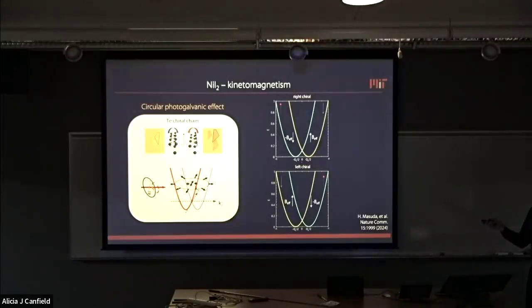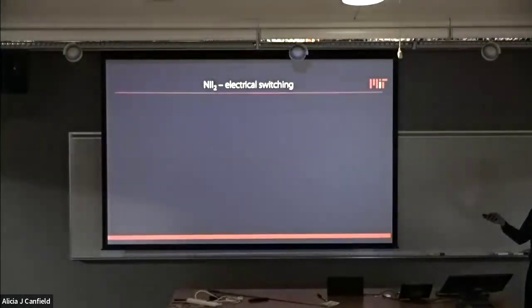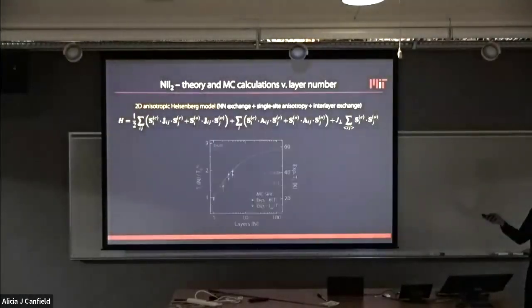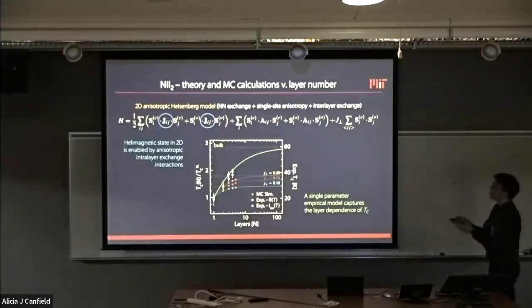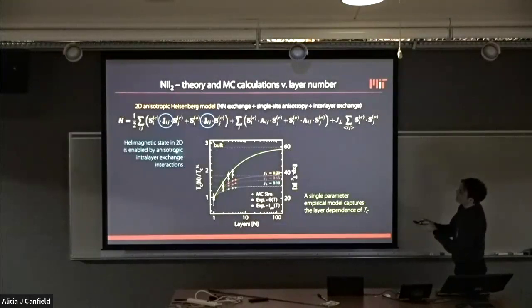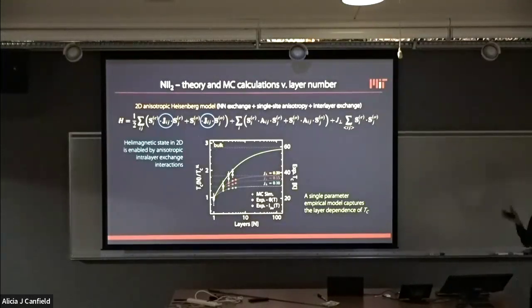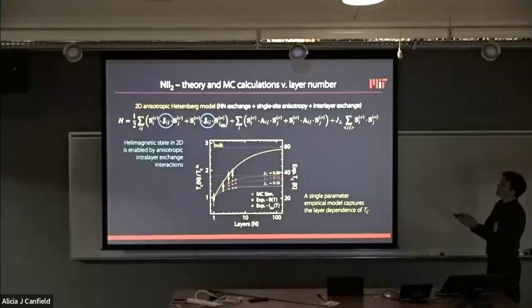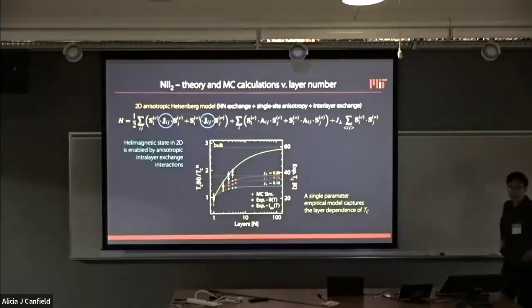I think in this material, anisotropic exchange might be probably more important than single site. Yeah, and sorry, I had to skip that in the interest of time. So the most key parameter in the model is this anisotropic symmetric intralayer. Oh, I see. Yes, so there's a full Heisenberg tensor, with nearest neighbor, secondary, and all the different pathways. Yeah, because of iodine, I would expect it to be more important than single site. Exactly.